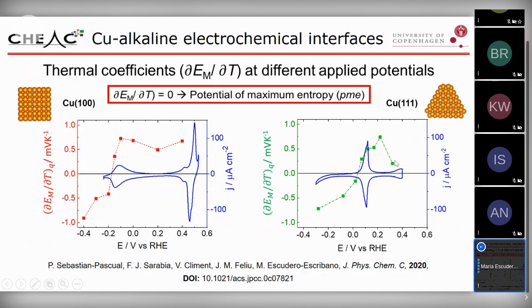And what you can see here is that at some positive potentials, this coefficient is positive, and then at negative potentials it is negative for both copper 111 and copper 100. The potential at which this thermal coefficient is 0 will be the potential of maximum entropy. Interestingly, the potential of maximum entropy is related to the onset of OH adsorption for both copper 100 and